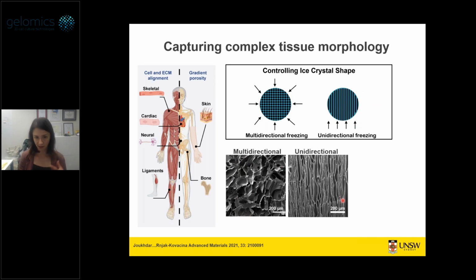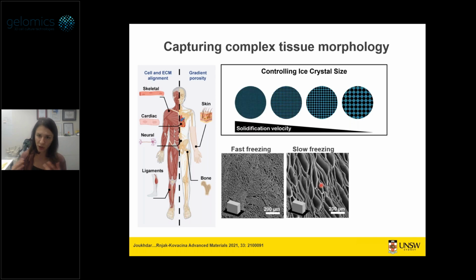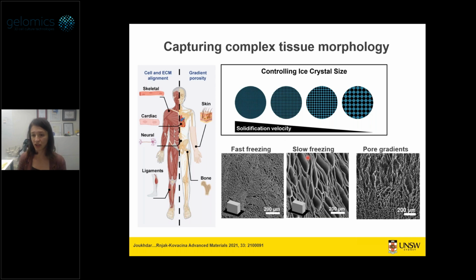Whereas if you change the freezing so it can only happen from a single plane, single direction, the ice crystals will start growing in a very elongated, aligned manner, and you're going to get these aligned pores. And this is now starting to look like the extracellular matrix of something like skeletal or cardiac muscle. And you can change the size of those pores by changing the freezing rate. As a general principle, if you freeze faster, you get smaller pores. And you can obviously engineer pore gradients. These are pore gradients in our silk scaffolds through the same process.